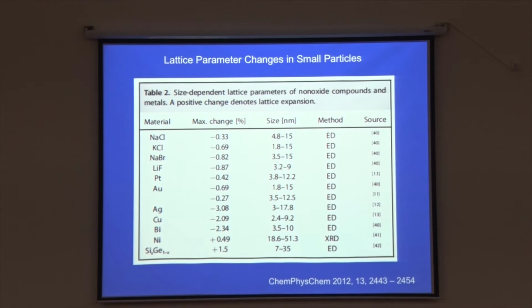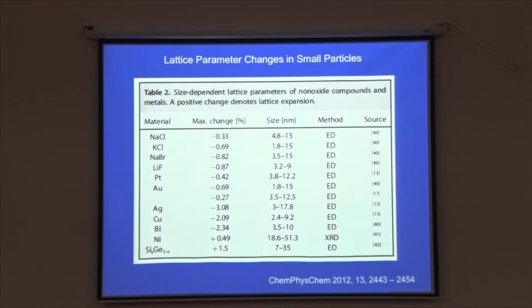In the literature, it is very well known that in very, very small particles we can get changes in lattice parameter. Lattice parameter characterizes the spacing between the atoms in the unit cell, for example. Because of this relaxation, the whole crystal as an entity can either expand or contract, and we can measure this difference in lattice parameter. What we wanted to do is to look at the relaxed structure of such wires, because as I told you, these are only 5 or 6 atoms thick. So there must be some dramatic relaxation that happens here.